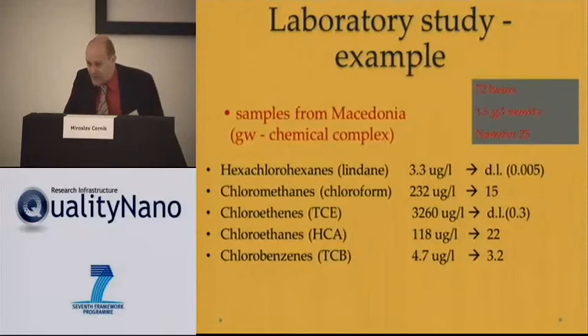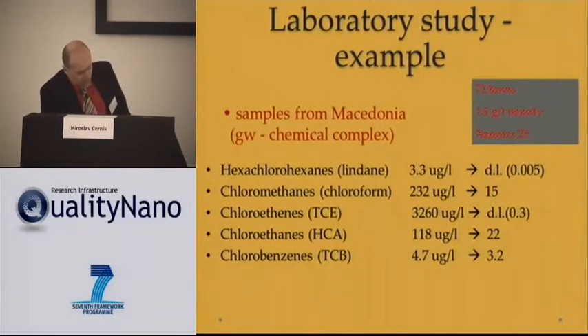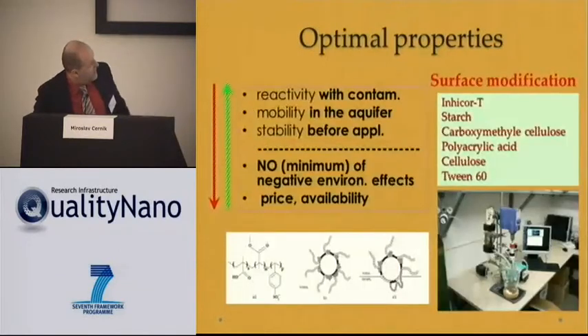We have here a small example from the laboratory. We had water from Macedonia, from some chemical complex where the groundwater around is very polluted by a really huge mixture of chemicals, from lindane to chloroform to chlorobenzenes, ethenes, ethanes, and so on. And we treated such water in the laboratory for 72 hours with 1.5 grams of nano iron, and you see changes in the concentration, so that we are able to reduce the contaminants below the detection limit in most cases. So this is, let's say, a simple example of how this nano iron works in the laboratory.